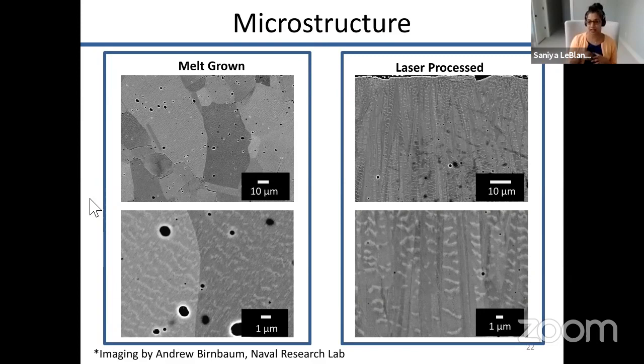And what you see there is these really long columnar grains that go through the thickness of the laser additive manufacturing part. So what this tells you in short is that doing this laser processing can allow you to control the microstructure of the material. That's really fascinating because if you think back to the beginning of the talk, I talked about how the structuring impacts the way carriers move through the material. It actually impacts the thermoelectric properties.